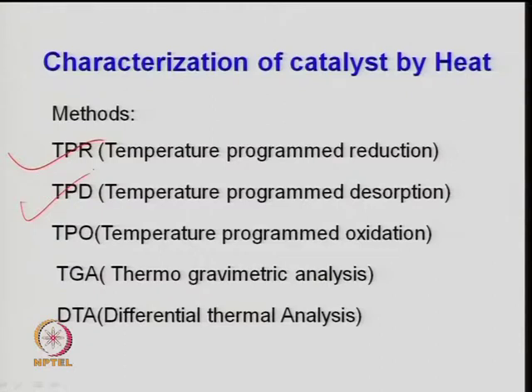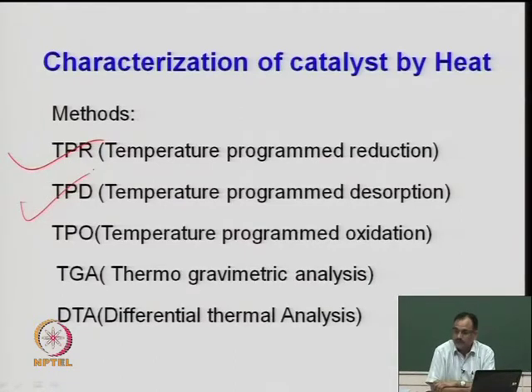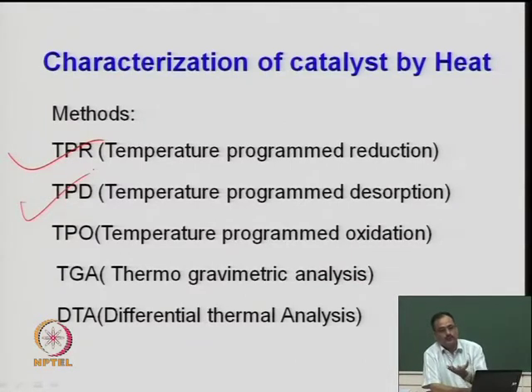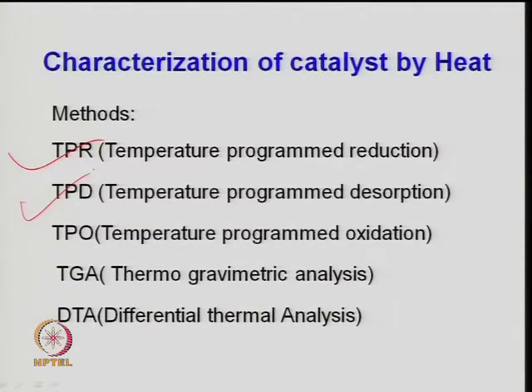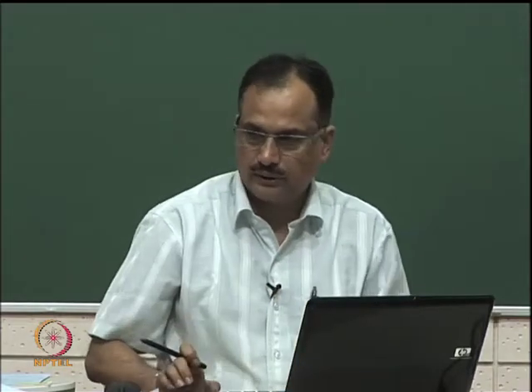In these techniques, you apply a heating rate — heating up to 1000°C at 10 or 20°C per minute — allowing kinetic study of adsorption, desorption, or reduction. TGA (Thermogravimetric Analysis) also can be performed with reactive gases like hydrogen, making it similar to TPR. TGA measures the loss in weight when you heat the sample through different temperature ranges at different rates. TGA and DTA are jointly associated: DTA gives the idea about endothermicity, exothermicity, and energy release during the steps when TGA is performed.